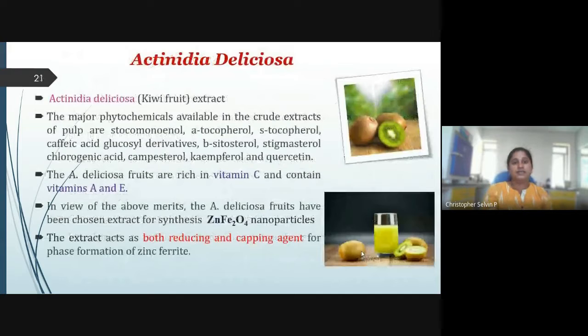So as mentioned earlier, we are getting into the green synthesis mode for preparing zinc ferrite nanoparticles. For that purpose, Actinidia deliciosa extract was prepared, which is nothing but kiwi fruit. The major phytochemicals available in the crude extract of this fruit facilitate the reduction of the metal salts into corresponding metal oxides. Further, this fruit extract is rich in vitamin C, vitamin A and E, which is highly beneficial for reducing the corresponding metal salts into metal oxides. So in this perspective, we are preparing zinc ferrite nanoparticles using the extract of Actinidia deliciosa.